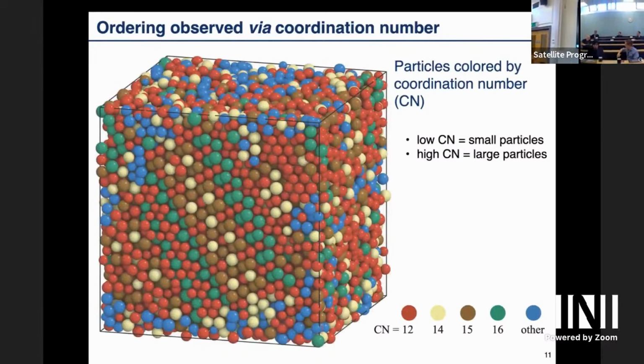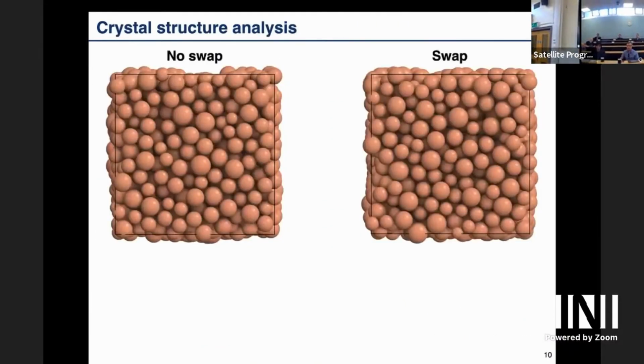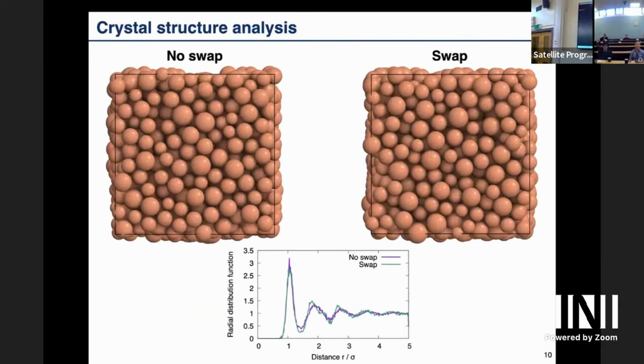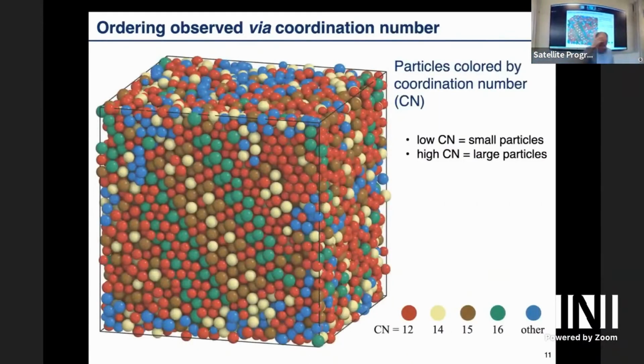What was the standard deviation there? This was 12%. So this was way above where you would get order normally. But with the swap, we can get ordering. This is a larger simulation than what I showed you before, because this one actually ran for probably a month or so. So my student ran it for as long as it makes sense on a computer.